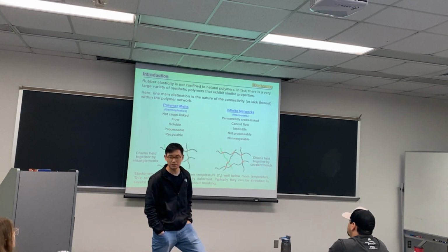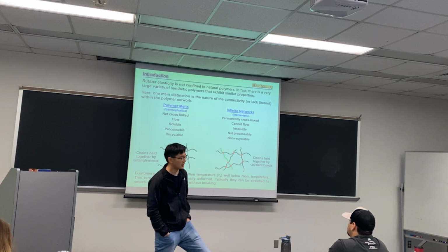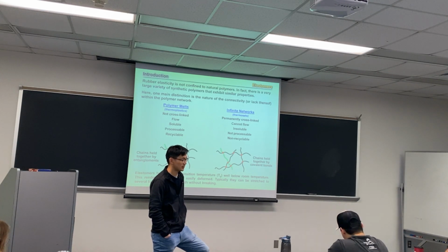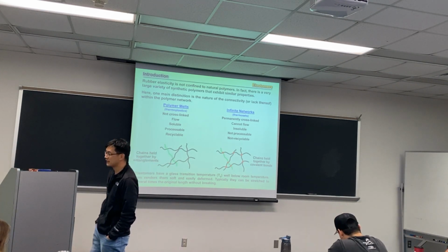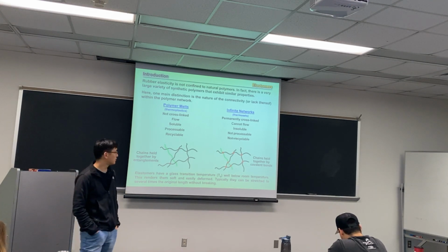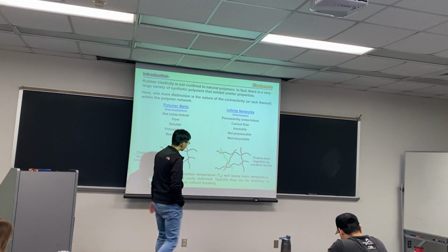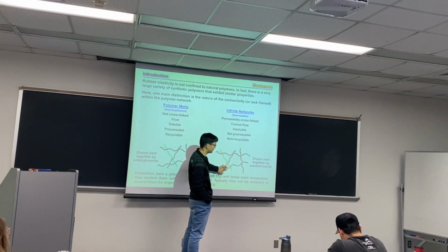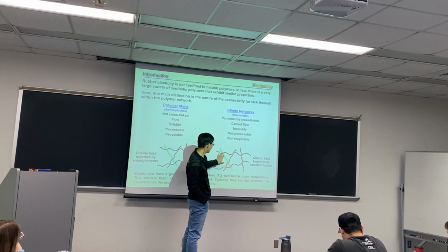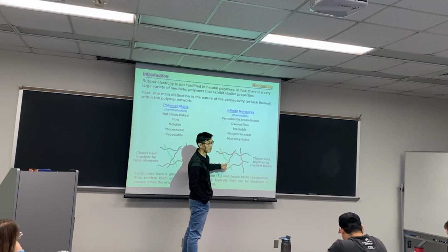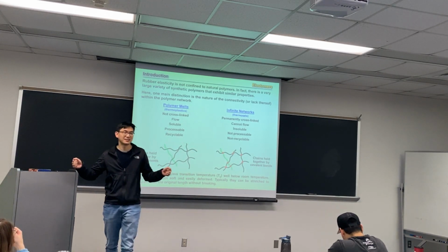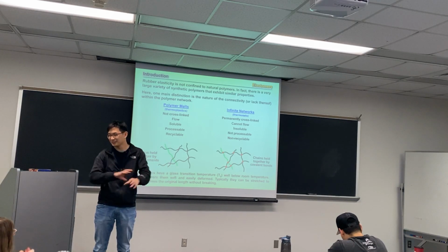So natural rubber is polyisoprene, and they would add sulfur to cross-link it, and that was one of the oldest ways people made elastomer. You add the sulfur, there's an unsaturated bond, and at higher temperature you would create these cross-link points. Okay, so it shows us here. For a long chain, the molecular weight could be very high, up to 1 million. And at different spots, it would randomly cross-link with other chains. So now if you think about it, you can deform these, they would elongate.